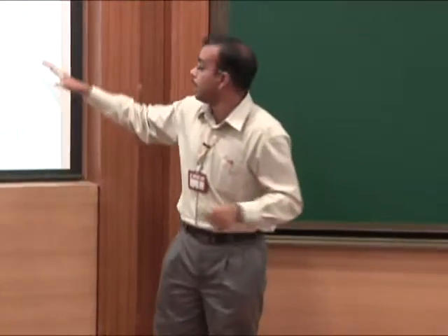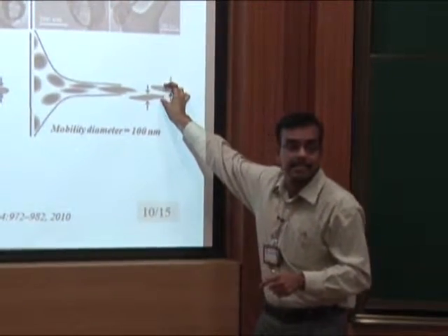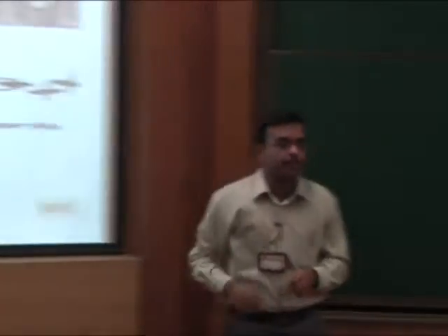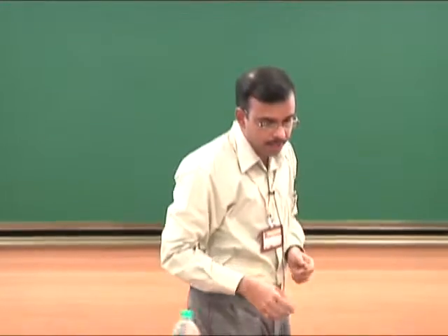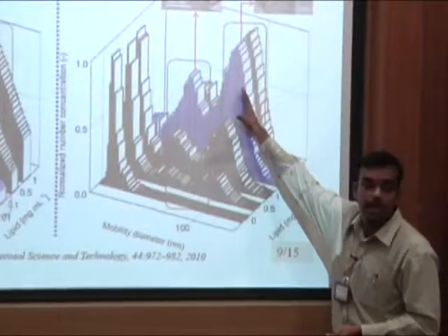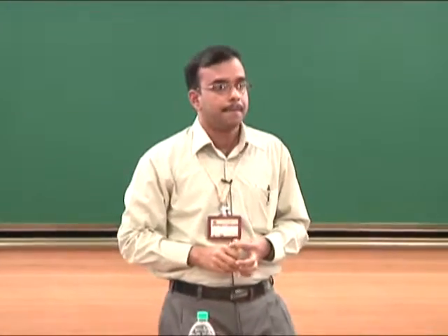We observed a number of TEM images, and we observed that the mean particle size is around 100 nanometer as far as this thickness is concerned. Maybe you have more than 2 getting stuck side by side, not only 2. Well, our result shows that we have 2 diameters. We pulled up the particles corresponding to this diameter and this diameter. So this shows that the particle size is clustered into 2 populations, one centered around 35 nanometer, the other around 100 nanometers. Okay. Thank you.